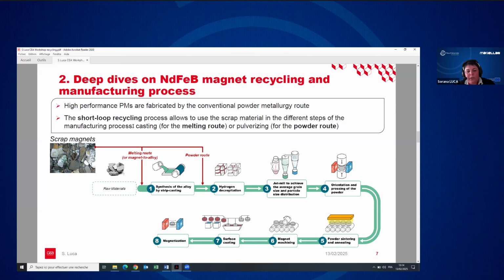In the short loop recycling process, so as I said, we introduce the scrap magnets at the different steps of this process. The melting route, or magnet to alloy also, we can call it, the scrap magnets are introduced in the casting alloying of the material, and in the powder route, we introduce the scrap magnets in the pulverization of the material.